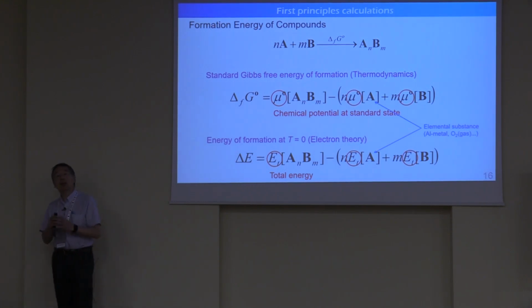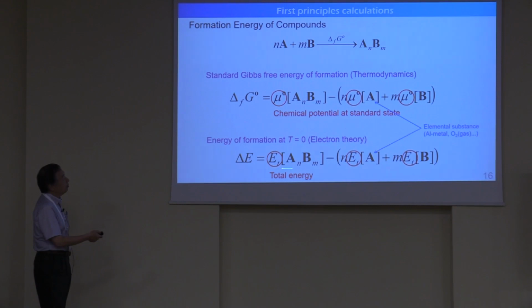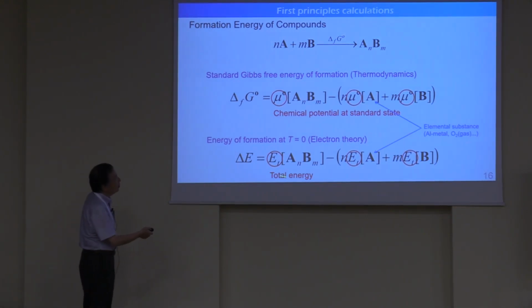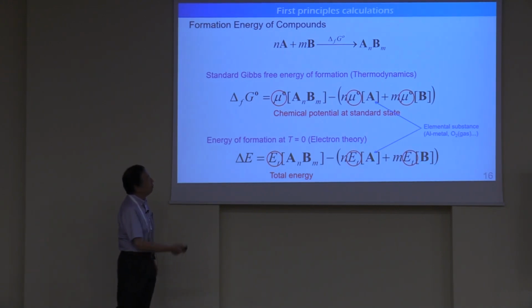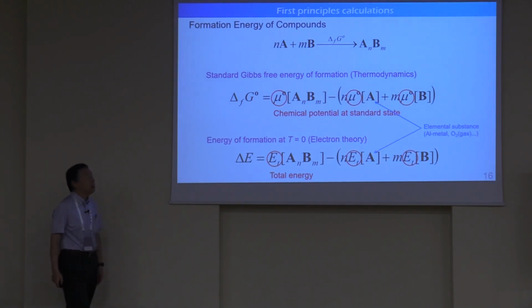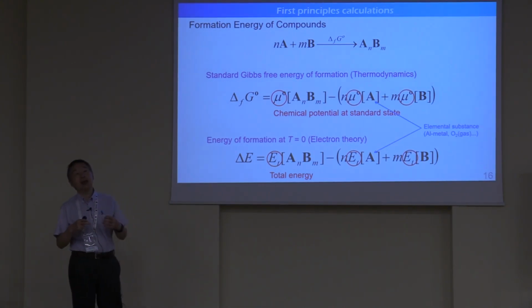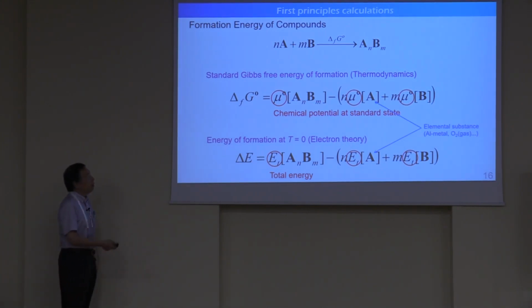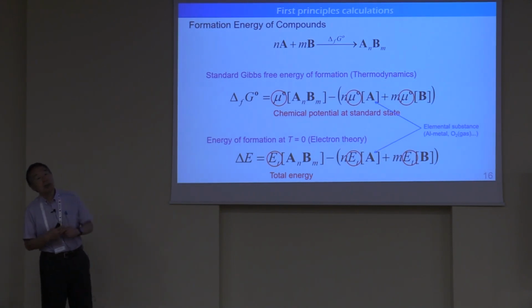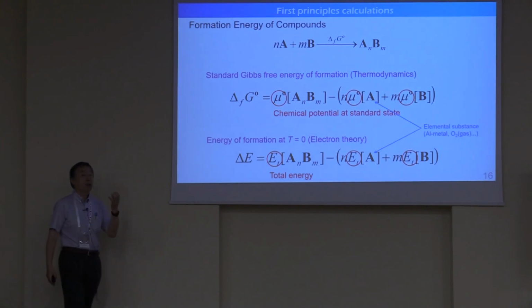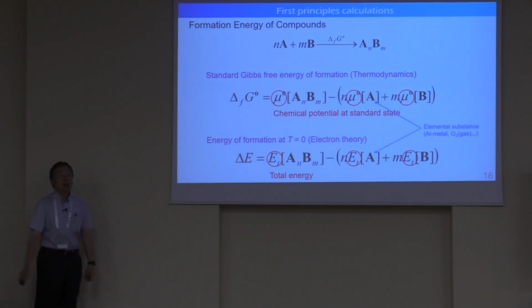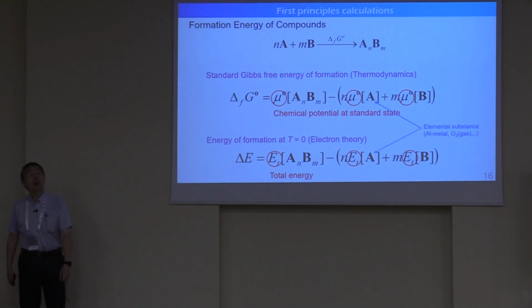By first principles calculation, we can do in the same way. We can just subtract the total energy of these substances with total energy of substance A and B. By that, we can obtain the energy of formation at 0 temperature. Of course, this is different from the thermodynamics, which is often used at 298 Kelvin or 25 degrees C. But other than temperature, the equation is somehow similar. And actually, in most of the materials, the temperature effect is not that much between 0 temperature and 298 degree Kelvin. So anyway, we can use this to measure the formation energy of this compound.